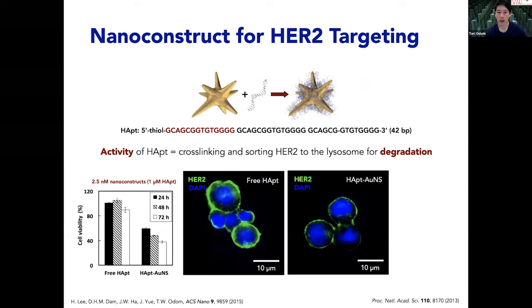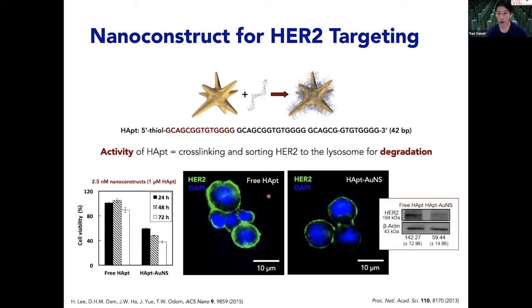And so you can see if we label the HER2 remaining on the cell membrane after incubation with the construct, you see it's indeed reduced, unlike the case where these cells are treated with the free aptamer. And then, of course, we needed to look at the actual protein content to quantify this effect, and not just looking at the decrease in fluorescence. And so in this Western blot, you can see that indeed there is significantly less of the HER2 left on the surface. Okay, so this is the system that we will work on, and we needed to understand the biology first.